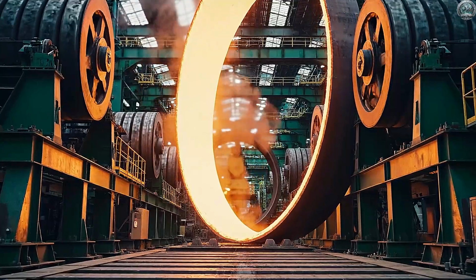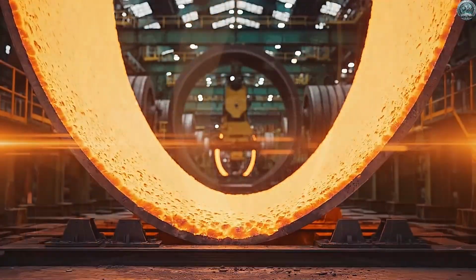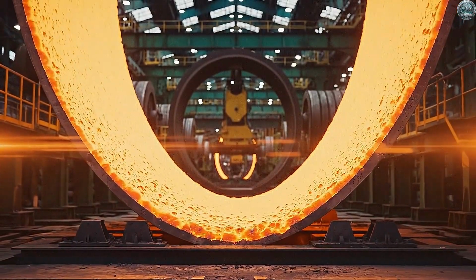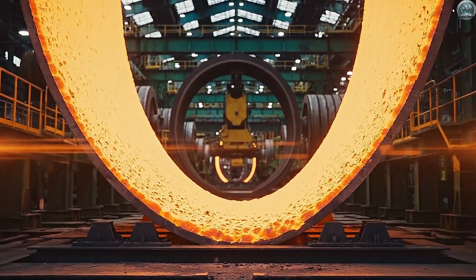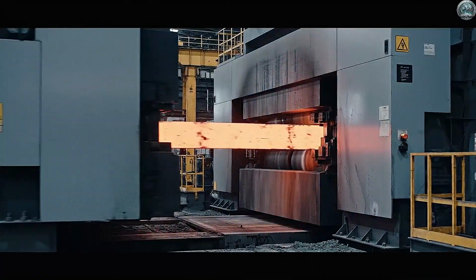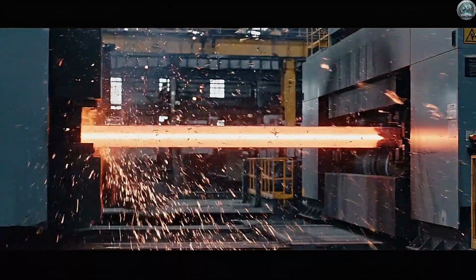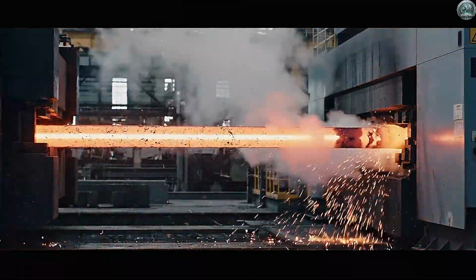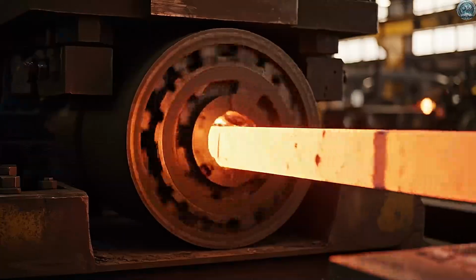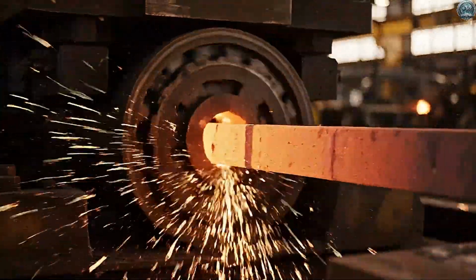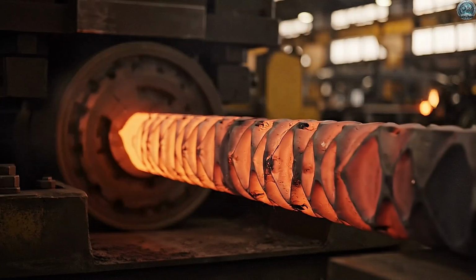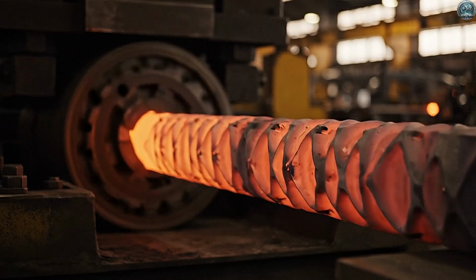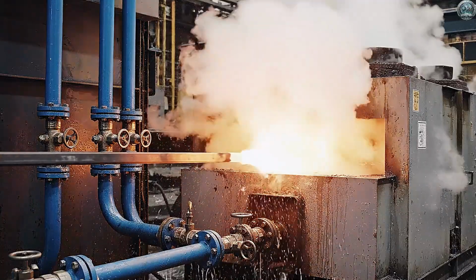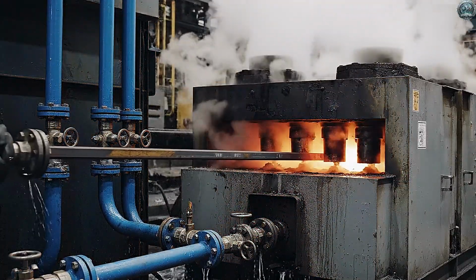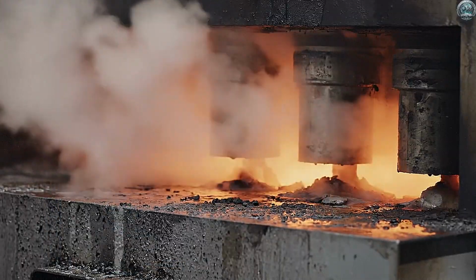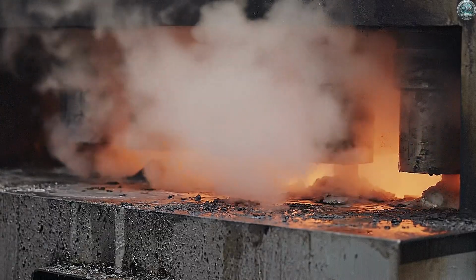Vertical loops relieve tension, allowing the glowing steel to dance gracefully between high-speed stands. Entering the finishing block, the steel accelerates to a blur, emerging as a precision-engineered rod. Microscopic precision rolls the signature ribs into the surface, ensuring the steel grips concrete effectively. A sudden blast of high-pressure water quenches the surface, locking in strength while keeping the core flexible.